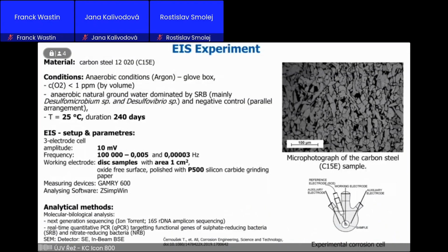So just now you can see an electrochemical impedance spectroscopy experiment under laboratory conditions to study microbial corrosion by sulfate-reducing bacteria. We used carbon steel. The experiment was ongoing under anaerobic conditions in a glove box, with an oxygen concentration below 1 ppm. The environment was anaerobic natural groundwater dominated by sulfate-reducing bacteria, mainly Desulfomicrobium species and Desulfovibrio. Also, a negative control without microorganisms was run to see the influence of microorganisms on the corrosion rate.